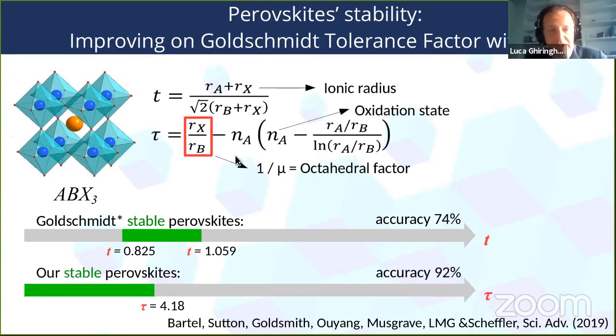So we ran our machinery and we found a slightly more complex formula, but using exactly the same ingredients: the so-called Shannon radii of the atoms. And we have the oxidation state that looks like extra information, but actually is also used for determining the Shannon radii. So if you want to know more, I can be more specific. But the catch is that we have this equation that is slightly more complex than Goldschmidt, and has a higher accuracy if we just split with a kind of sharp step at this value here.